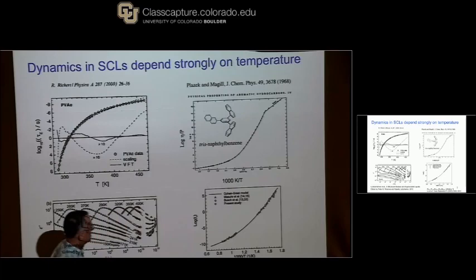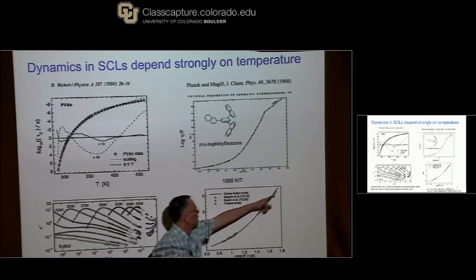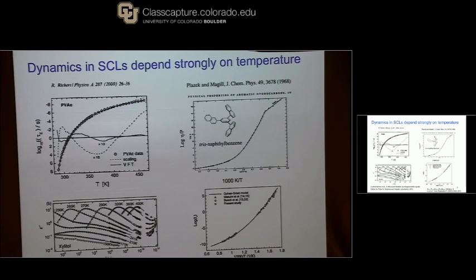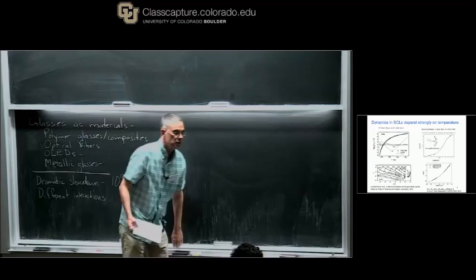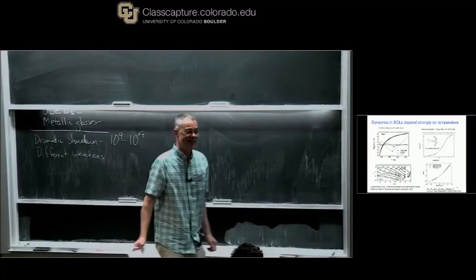The final example is a metallic glass. What's plotted here is a mechanical experiment: you deform the sample a small amount suddenly and you measure how long it takes the force to decay with time — a stress relaxation time. Those times go up to about a day here, 10^5 seconds at equilibrium, covering a total of about 14 orders of magnitude. So there's a range of different methods that can be used to measure the slowdown, for different materials and different interactions between the molecules or atoms.